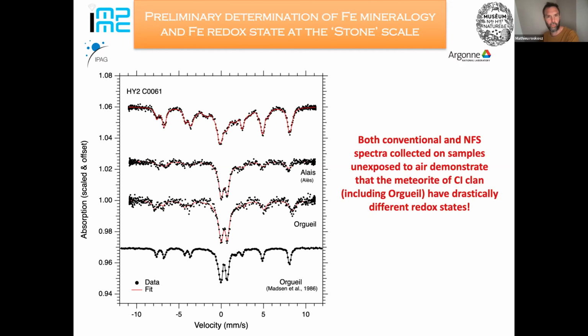So this is the proof, and this was one major point of the Science paper. This is the proof that actually probably the CI material that we have on Earth has been badly oxidized during the last century, and that the pristine material for CI chondrites and CI asteroids is much more reduced. It's about 50-50 iron 2+ and iron 3+.